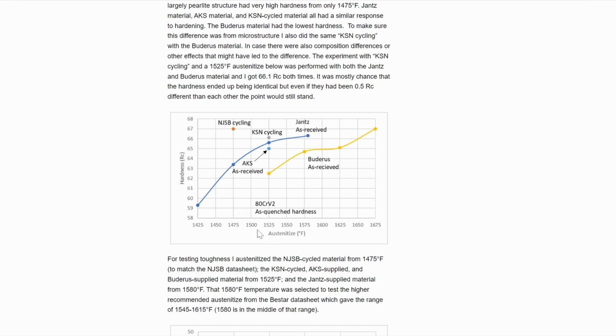So here is hardness versus austenitizing temperature for a 10 to 15 minute austenitize before quenching. So this is the Buderus material from New Jersey Steel Baron. You can see if you use 1525 as quenched, you'll get 62.5, versus my recommended cycling where you would get 66 Rockwell as quenched. And to get that type of hardness with the Buderus material, you'd have to be up into the 1650 range, which is pretty hot for this type of steel.